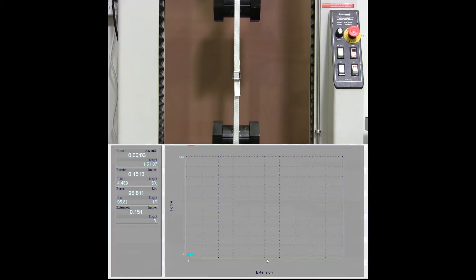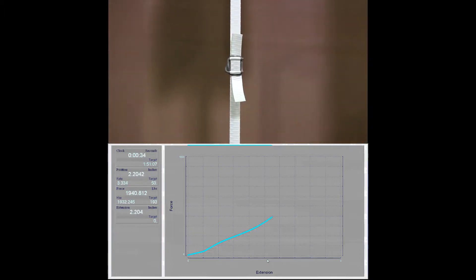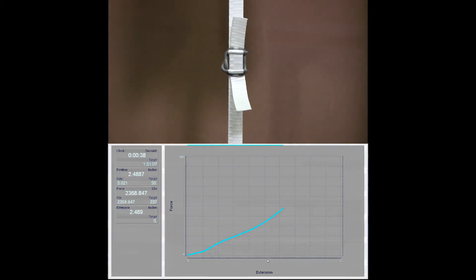Here's our 2,425-pound CW7525 woven strapping with our standard BF1940 phosphated buckle. As the extension of the pull is charted on the horizontal axis, strength is recorded on the vertical axis. The result of this test was 3,171 pounds, and our PC controller recorded no slippage.